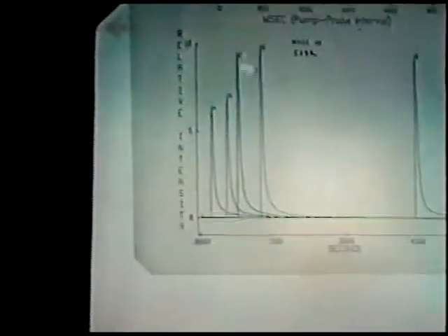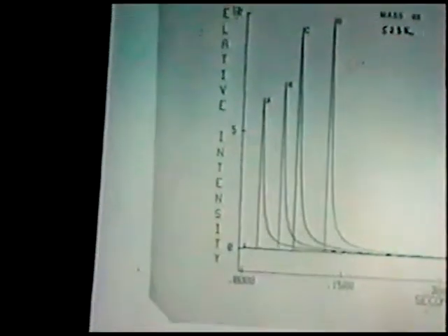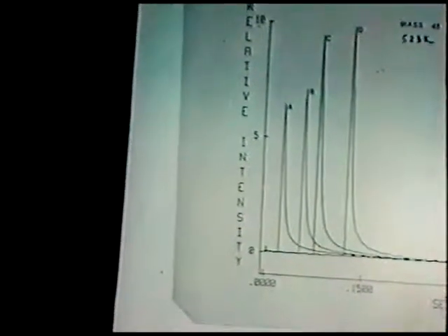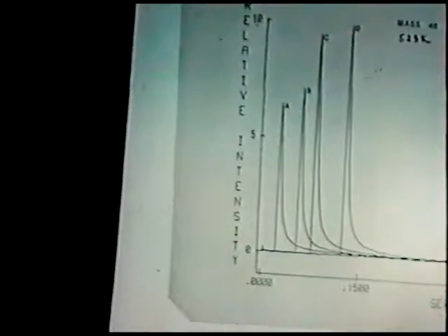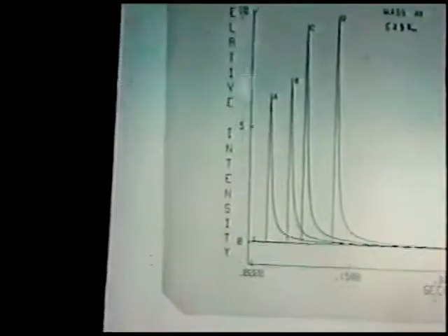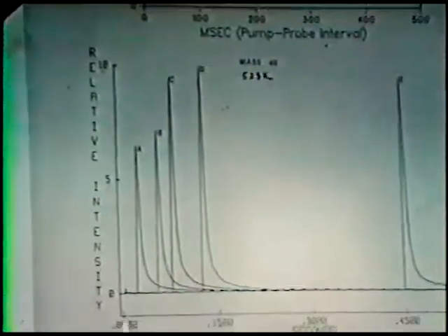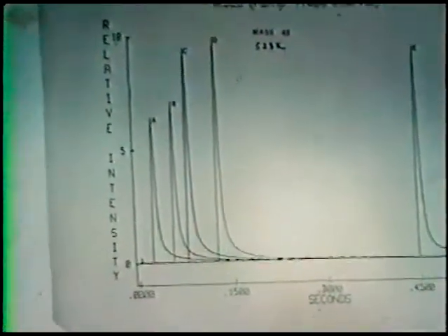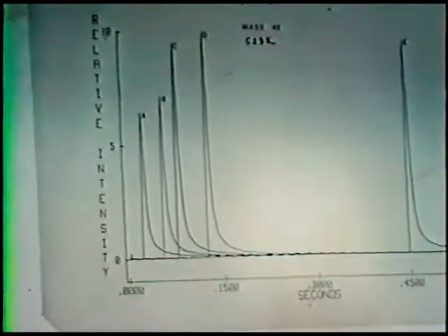It could also be that there are certain residual surface species, such as surface carbonate, which retard the formation of ethylene oxide initially, and then after a longer delay time are washed out of the system and don't have any further effect. But I think it's interesting at least to point out that these kinds of effects can be observed in this type of reactor because of the possibility of injecting these sequential pulses on such short time scales.